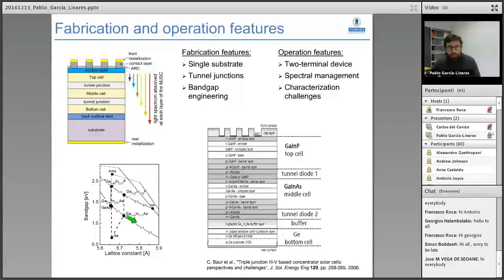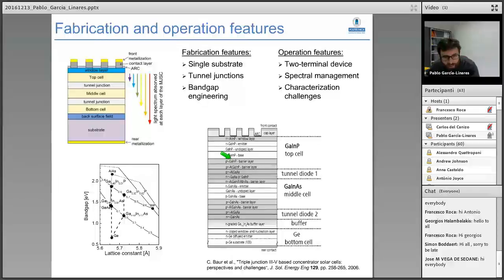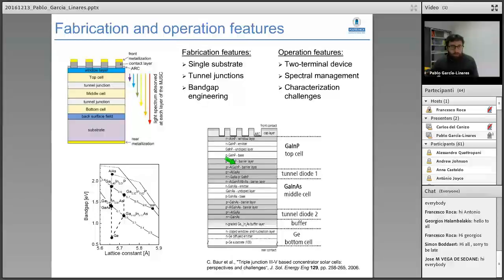In the state-of-the-art solar cell we use triple or quadruple multijunction structures. The gallium-indium-phosphide, gallium-arsenide, and germanium configuration is the typical lattice-matched approach. We can also think of lattice-mismatched approaches with some subcells slightly deviated from the lattice constant of the substrate — these are called metamorphic structures. This lattice-matched multijunction approach has many epitaxial layers and is quite complicated to fabricate and operate.